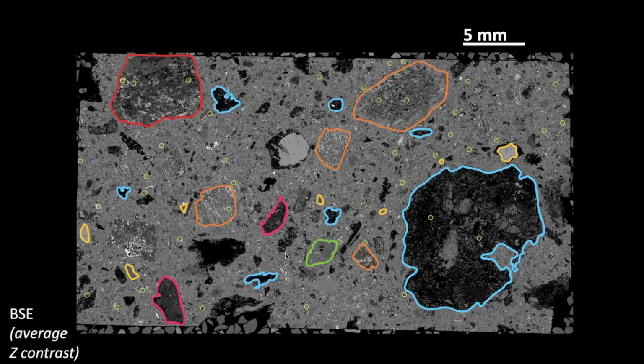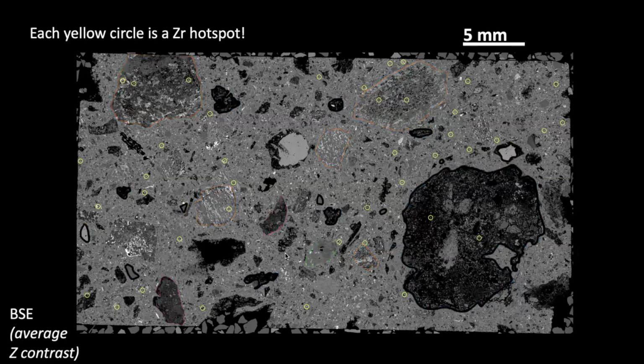So they have the same chemistry, but Reidite is like 11% more dense. You can actually see that in backscatter electron imaging. So each yellow circle here was a zirconium hotspot that I mapped with WDS. So I went to each of these locations and I investigated. I imaged it at higher magnification with backscatter electron imaging.